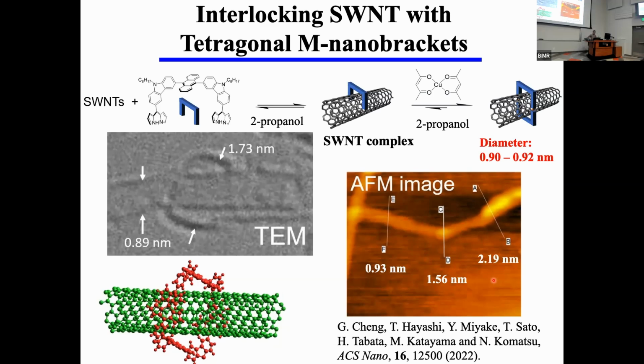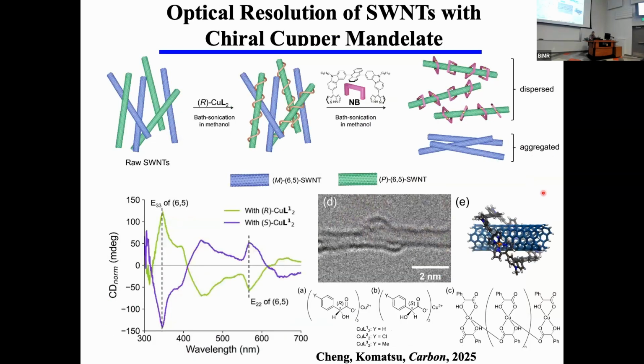size selective properties. And we found that the diameter range of the enriched carbon nanotube is from 0.90 to 0.92, only in the range of 0.02 nanometer. And so here is another example of the host molecules. We just change